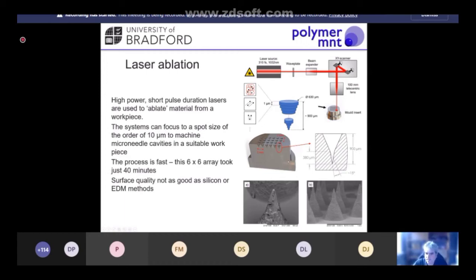But the main advantage is it's low cost and it's fast. So this 6x6 array just took 40 minutes. The EDM mold that I showed on the previous slide took about a month to machine every single laminate to form that tool, which is clearly much more expensive as a solution. So laser machining is great. It's fast and low cost. The problem is it maybe doesn't offer exactly the same level of surface quality as the EDM technique. So you see here we have a slightly rougher surface finish, but for a majority of applications, it works very well indeed.